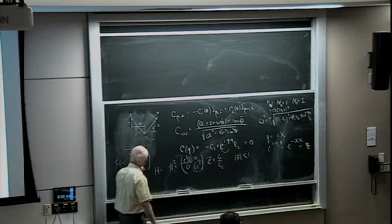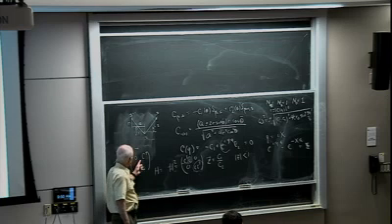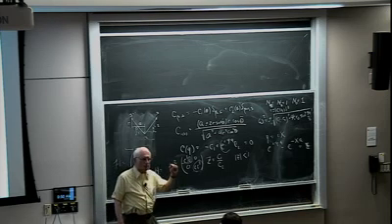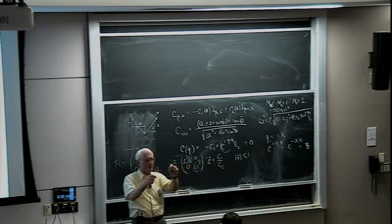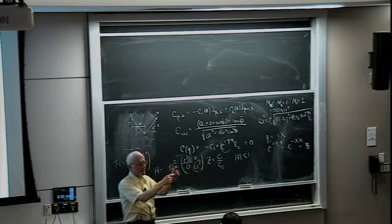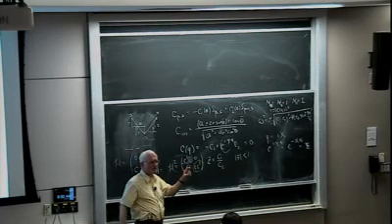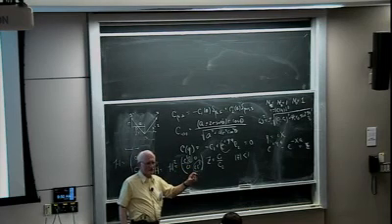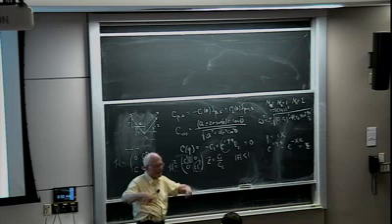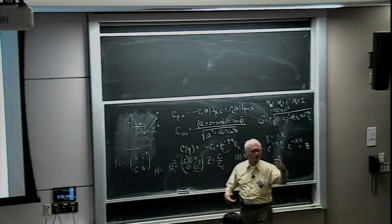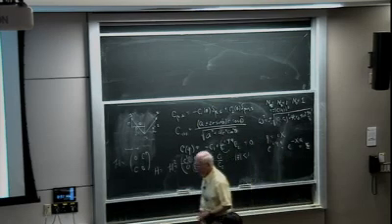Correct. And so when you look at it this way, this couples bonds to sites, and it turns out that when you look at the 0 mode there, it depends on how you terminate your system. If I terminate with the double bond, the displacement or the electron occupation of every other site is actually 0, but that's telling us that the bonds don't stretch. So there are a lot of these analogies which take a lot of time to deal with. Maybe we can spend a little time later on talking about that.